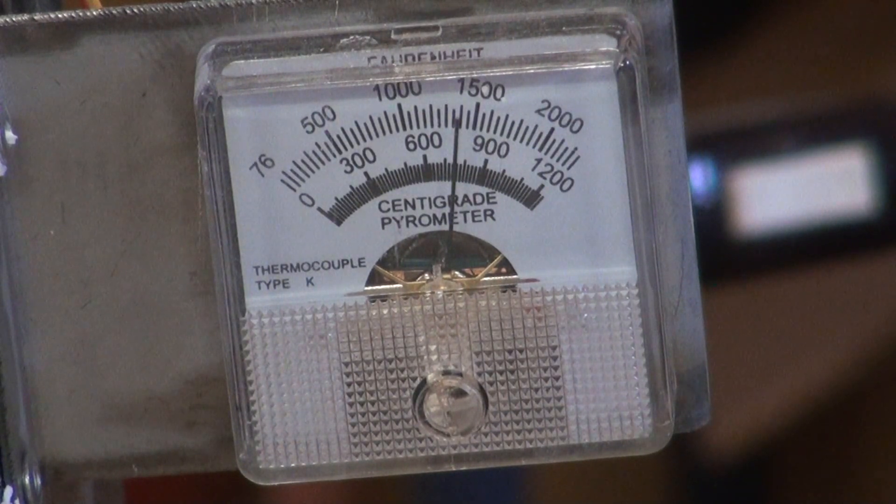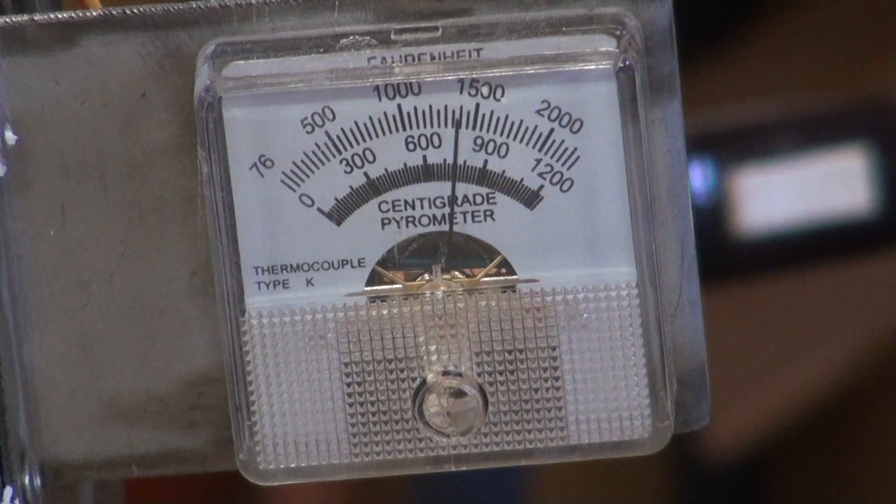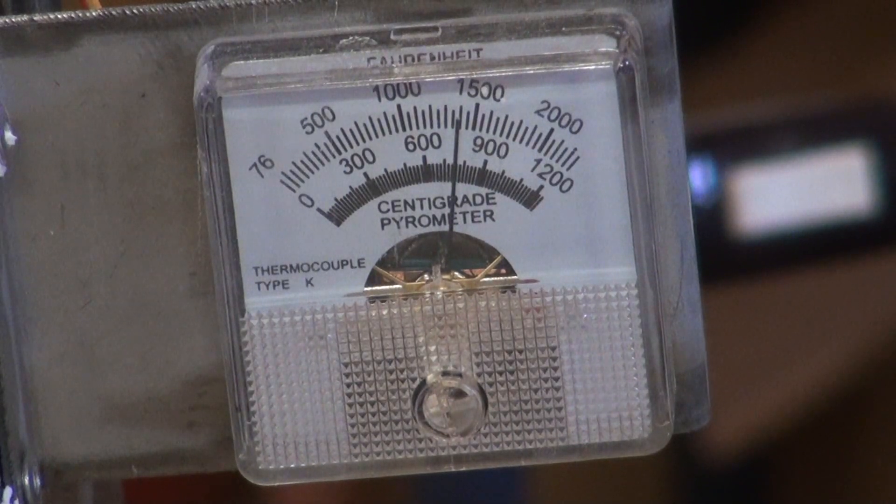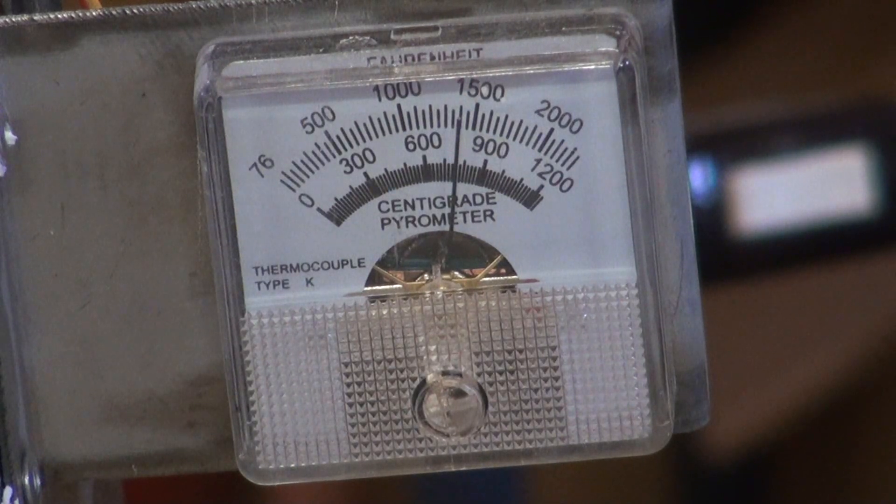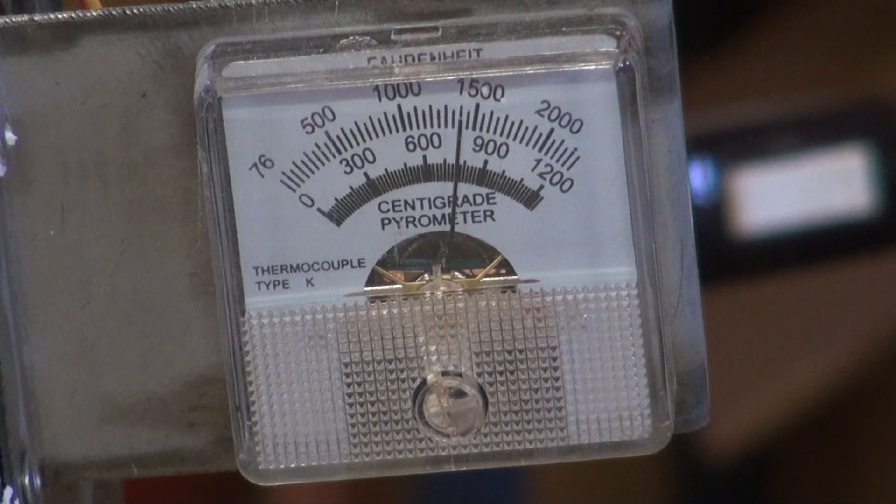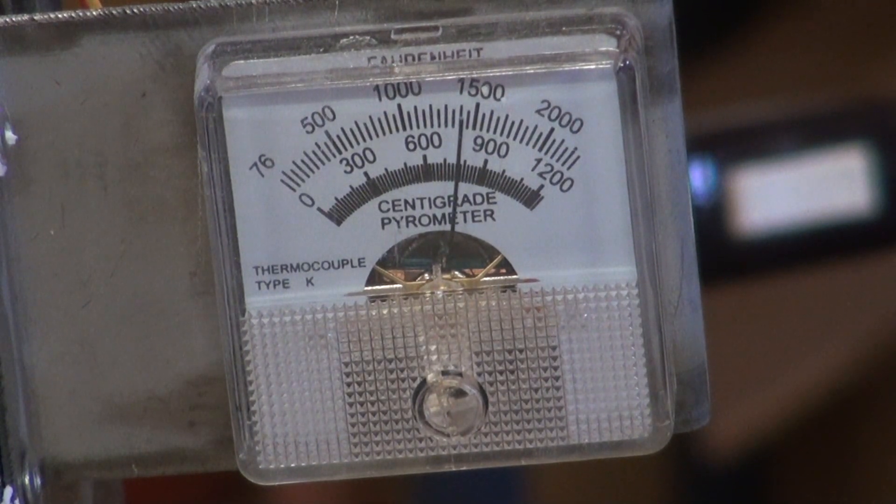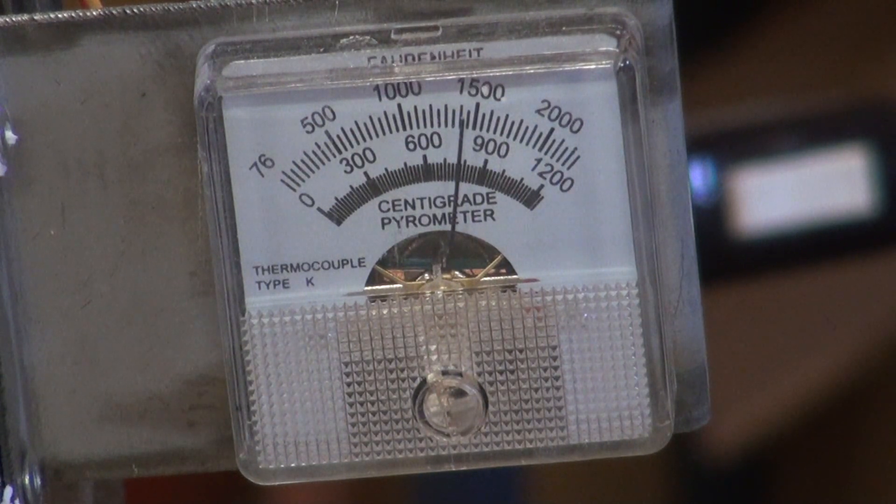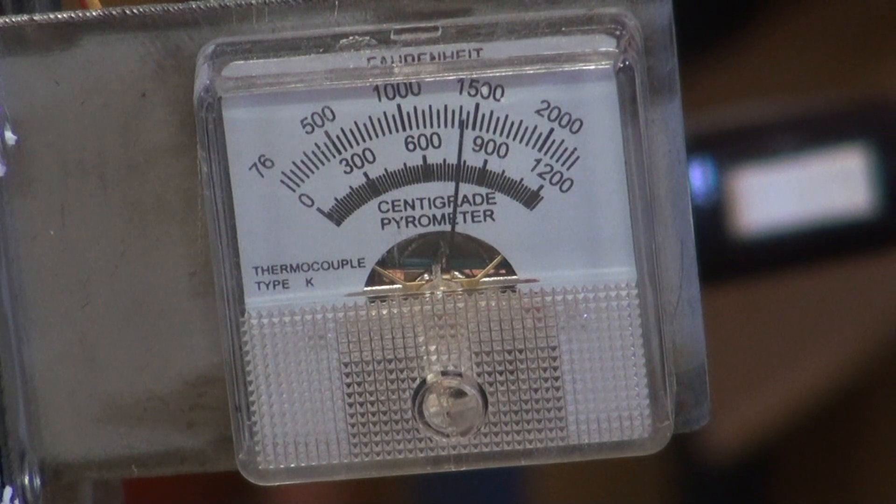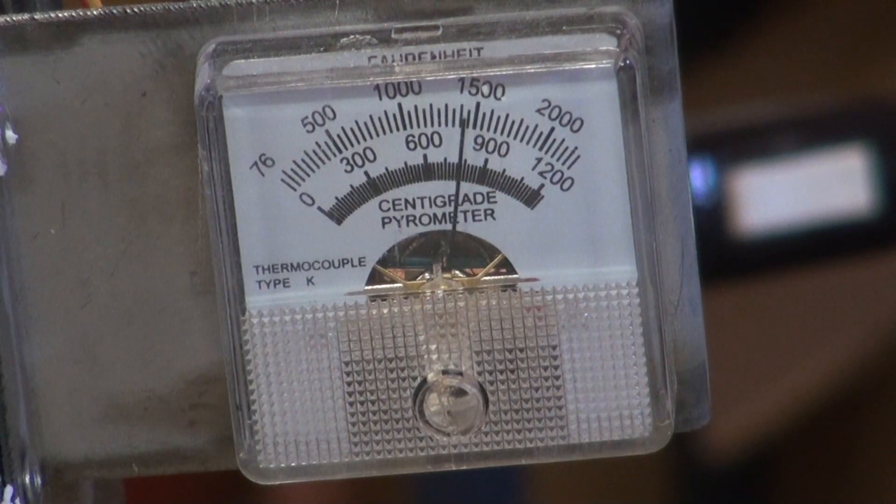You may wonder why we can go so rapidly to that temperature and back again. The reason is the piece of glass is fairly small. Also, we're going to cut a pendant out of this glass, and when we fire polish the edges, we'll have a chance to anneal the glass again to make sure that it doesn't crack. So we'll take it up to 1800, we'll turn it off. When we come back, it'll be time to cut out our shape of our pendant.